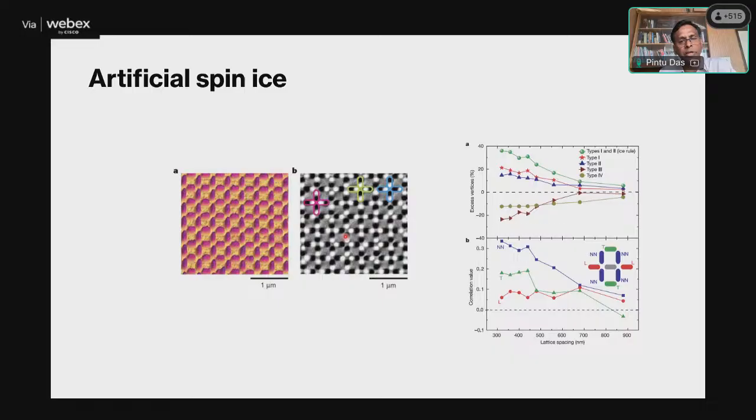In magnetic force microscopy, you measure the gradient in the stray field of the vertical component of the stray field. You see that each of the nanomagnets shows black and white patches, which means these are single domain. If you consider these as magnetic charges, white is where the arrow points, and black is the tail of the arrow, right?